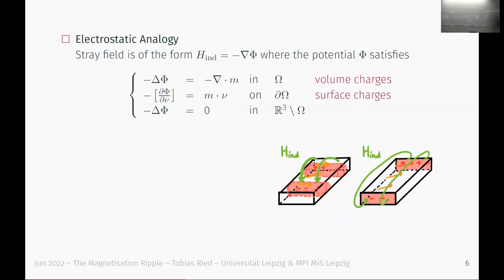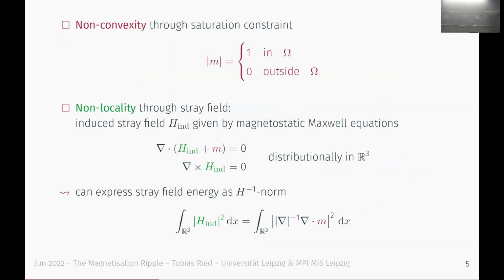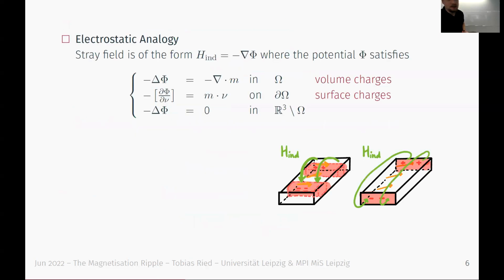To understand this induced field a bit better, it's a good idea to write the stray field as the negative gradient of a potential, and that potential reveals some nice analogy to electrostatic thinking. Since we are really interested in a finite material, if you look back to the Maxwell equations, this is satisfied distributionally in R3. So we have some interior terms, so the divergence of H is related to the divergence of M, but then we also might have boundary jumps because we have a magnetization that jumps from something to 0 on the boundary of the material.